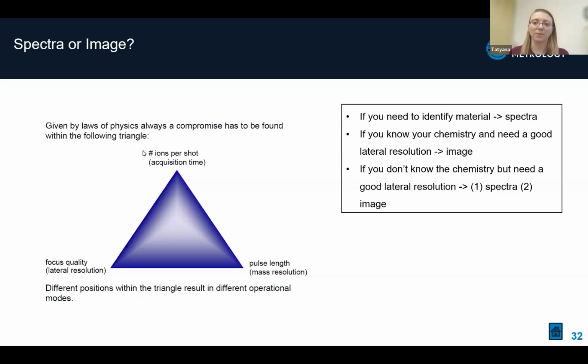The key point here is that you can't optimize all 3 simultaneously. Different positions in this triangle represent different operational modes, and we need to choose our position based on our specific analytical needs. Looking at the box here, this is how to decide. If your primary goal is material identification, you will want to prioritize spectra. If you already know your chemistry and need good spatial information, go for imaging. And in the case where you're not certain about the chemistry but still need good spatial resolution, you will want to first get the spectra, then capture the image.